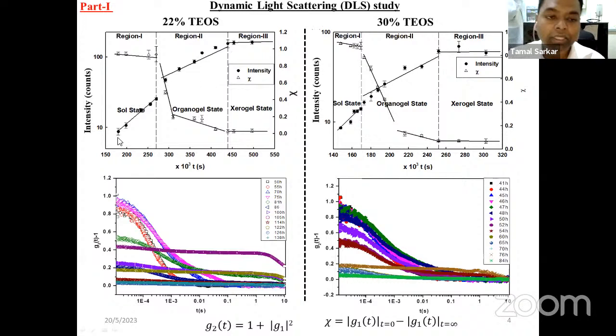Now in the first state, I see the intensity increases from this point to this point. In this region one, the siloxane bond started forming the chain-like structure, and by this time all the chains got interconnected and formed a gel. And from this point onwards, the gel starts releasing its interstitial solvent, and the gel becomes very, very rigid from this point to this point.